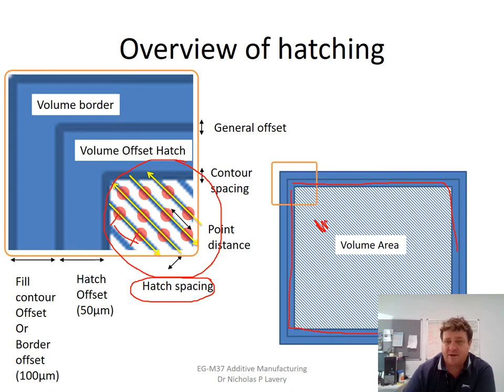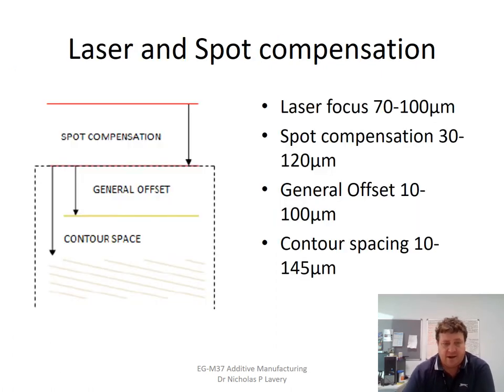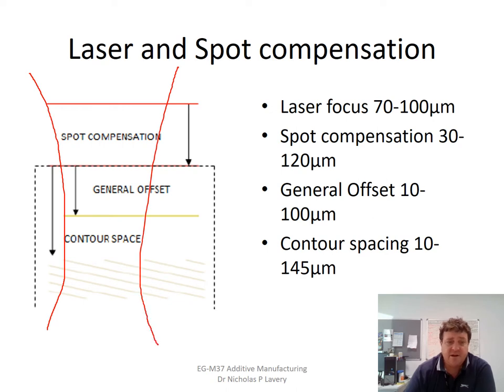These are pretty standard. The laser itself is focused so that it comes down with a kind of semi-conical focus like this, so that you have a distance above and below the optimal that allows you to offset the focal area. Typically, the diameter of the laser focus is somewhere between 70 and 100 micron. With some machines, you can vary this, and that becomes one of the machine parameters that you can vary. In others, they are pretty much fixed.